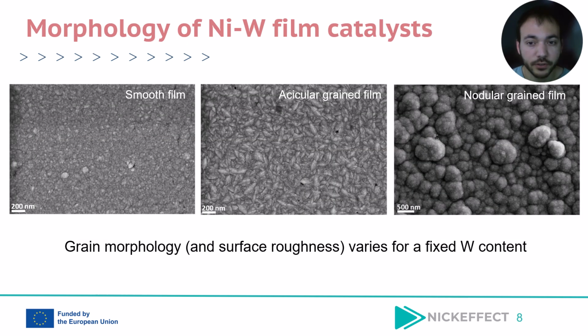As you can see in these same images, we can obtain different morphologies by just changing the deposition conditions, going from a nearly smooth sample to acicular grain films, and finally to nodular grains at high temperatures and current densities. So even with nearly the same concentration of tungsten, we can modify the surface of the samples, which is a key parameter for catalysis.